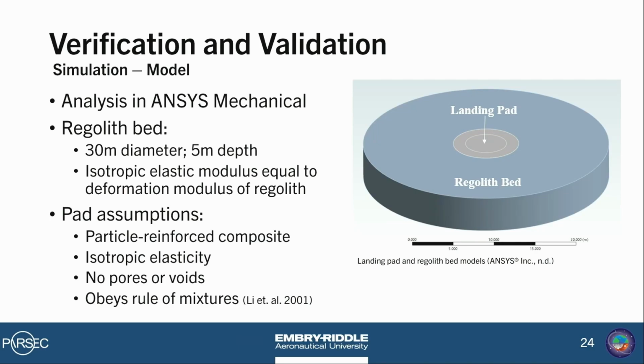So to get a better idea of the stresses that a real landing pad would experience, we did develop a heavily simplified model of a landing pad and regolith bed. Using this model, we conducted static structural analysis in ANSYS Mechanical, where we applied a 65 kilonewton load to the landing pad to simulate the load of a 40-ton lander.